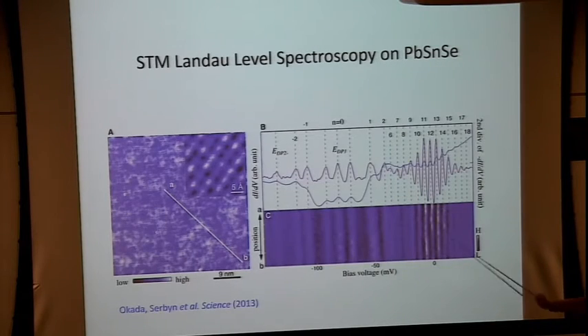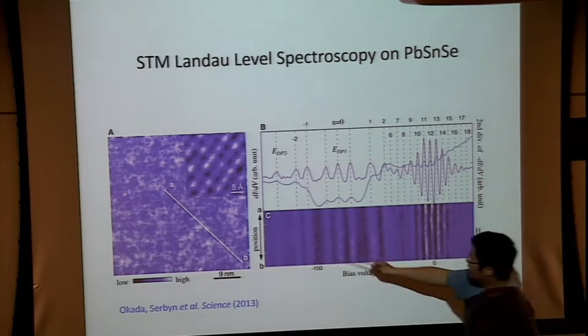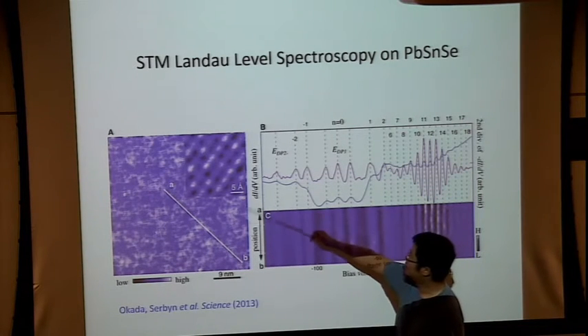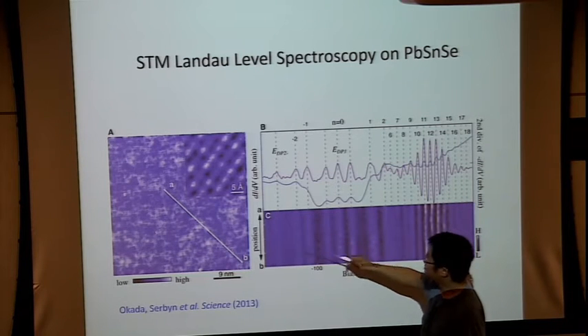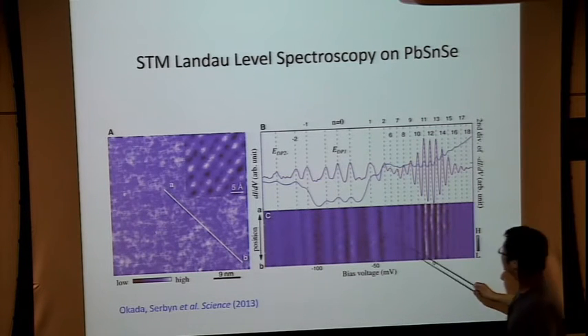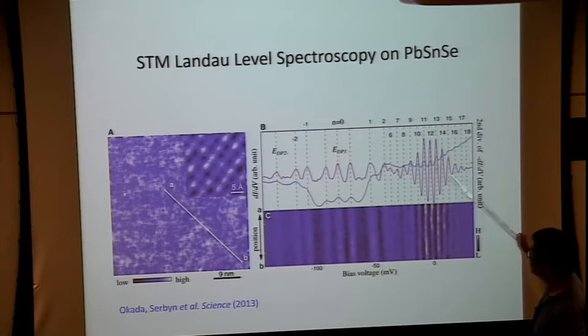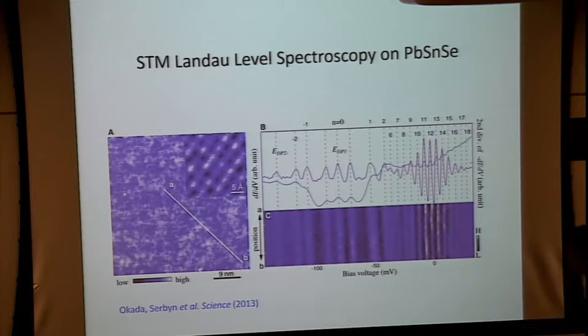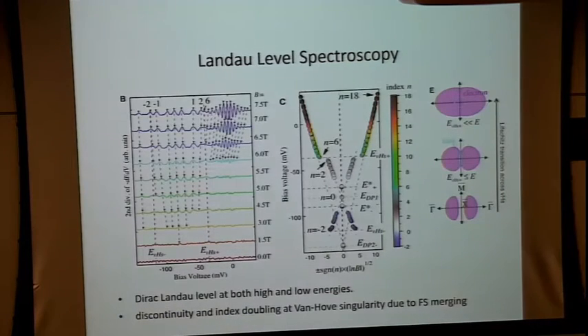Now experimentally, the Vidya Madhavan group actually used STM to look at this compound, lead tin selenide. It turned out to be very interesting. So this is an alloy, lead and tin. They mix with each other. So in topography, it looks like a mess. But when you turn on the magnetic field, you see that the beautiful Landau levels show up. These are Landau levels coming from the surface states, and actually the mobility of the surface states is extremely high, so that you see the Landau level energy is basically independent of position over a length of 30 nanometers or even longer. So the quality of the sample is pretty good.